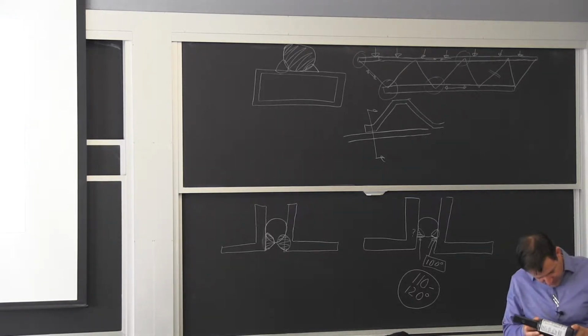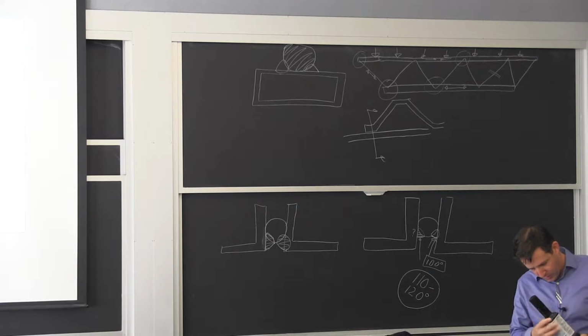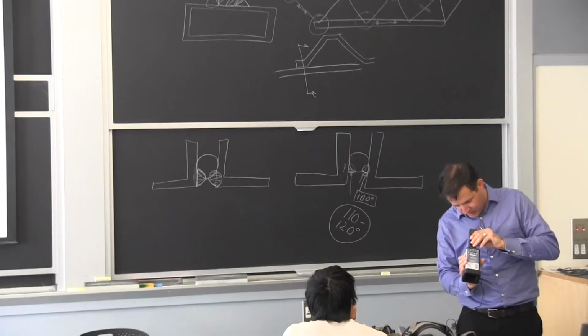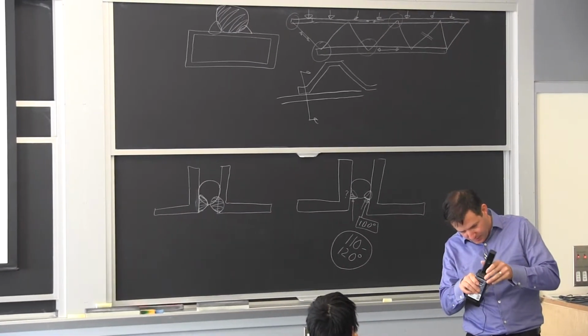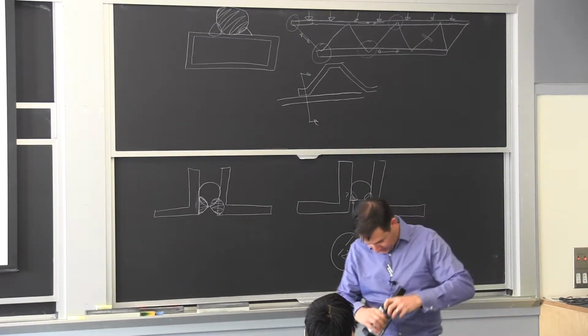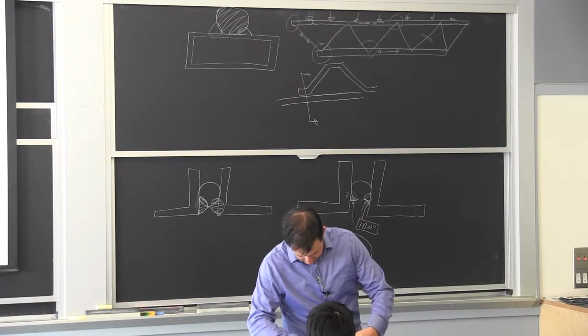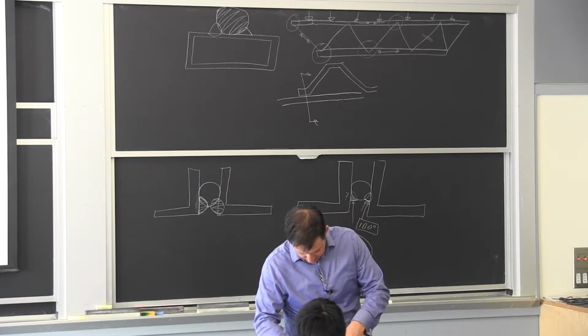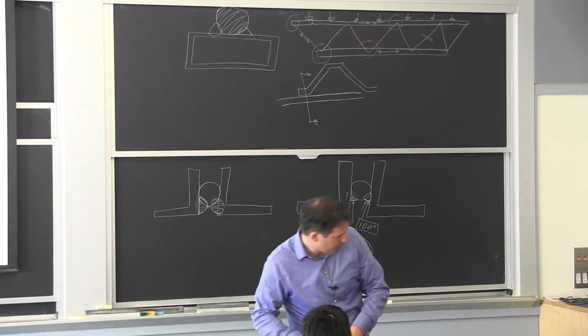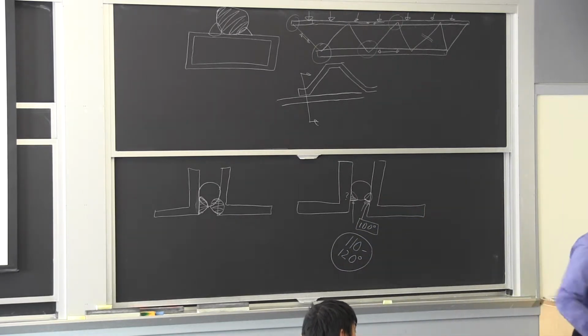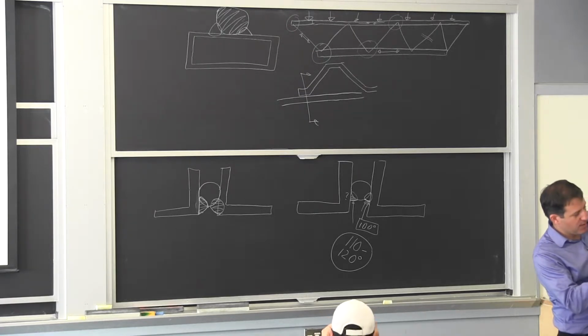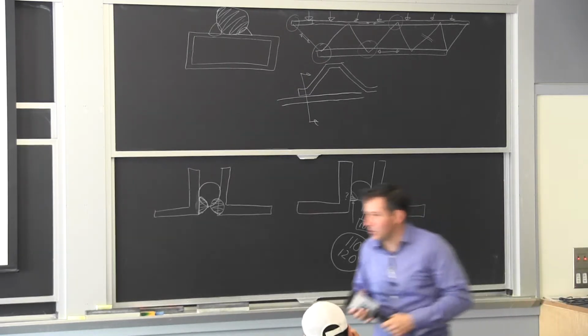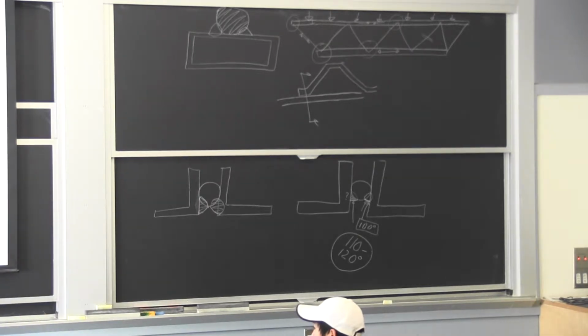There's very little area that I worry about the fusion here, but there was one that I looked at and I wasn't really sure. Look at this spot here. You can see that it was really welded this side, so this would be the one spot that we'll have to check, and I mark it. At that corner, we're looking at the outer weld as being the one that, you look at it from the side, it's probably 95 degrees. Be careful with it, but it's not super heavy.